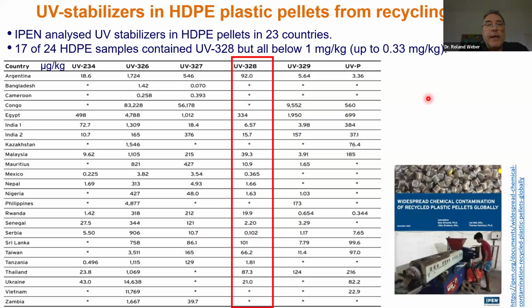Then there is a second study from the International Pollutant Elimination Network. They have analyzed high-density polyethylene pellets for UV stabilizers in 23 countries. So they found 17 of the 24 high-density polyethylene samples positive for UV328. So this is a much higher share than our study from the Global Monitoring Plan. But why? The reason is that they used much lower detection limits. So they went down 1 order of magnitude more in detection limit and quantification limit. And by this, then in many samples, they could find the UV328. But all of these samples were below 1 milligram per kilogram.